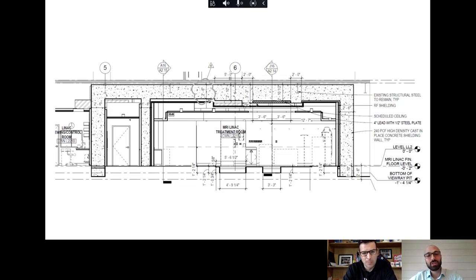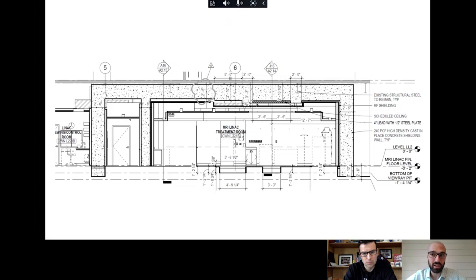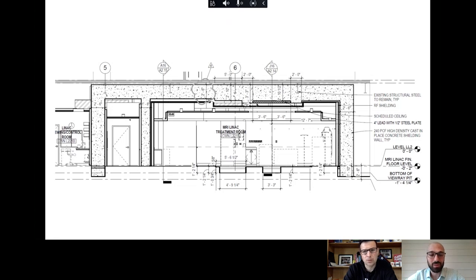So now we had to set out and create a mix that would be strong enough, because this is a very heavy structure. It had to be strong enough to support itself. It had to be dense enough to serve as a radiation shield. It had to be workable enough that we could actually pump it into place. And all those things are sort of in conflict with one another. So one of the hardest parts of the project was actually getting, but it had to be non-ferrous as well, because it couldn't interfere with the magnetic imaging. So Boston Sand and Gravel, I may have worn their patience thin with the amount of mixed designs we put together.